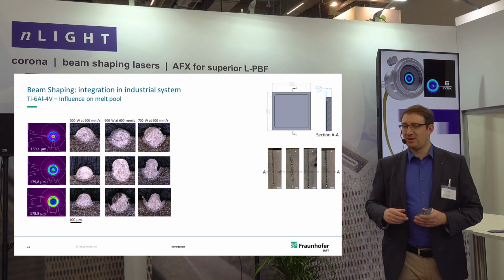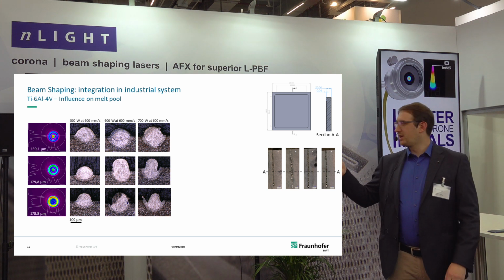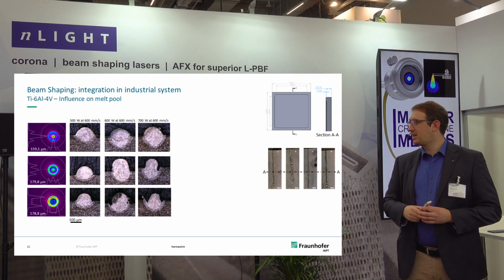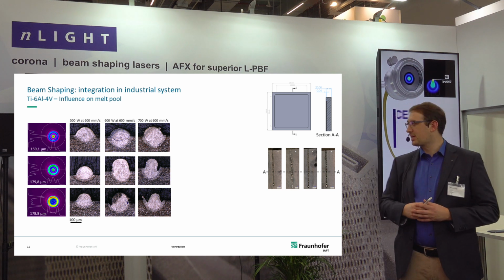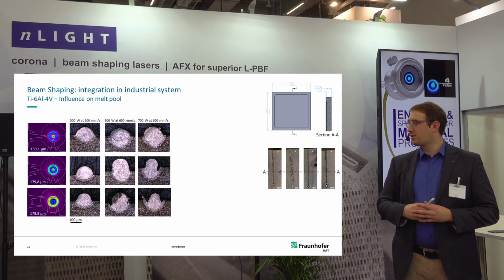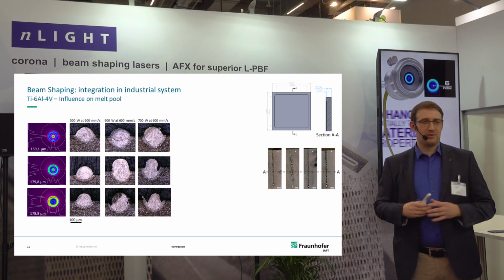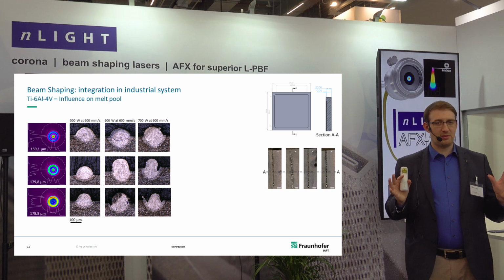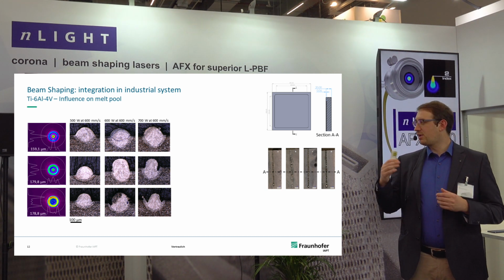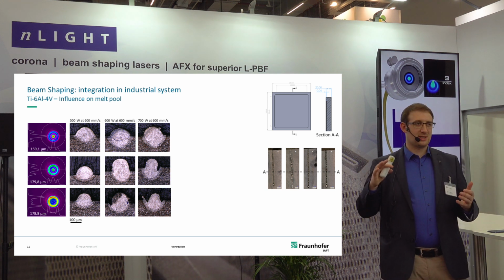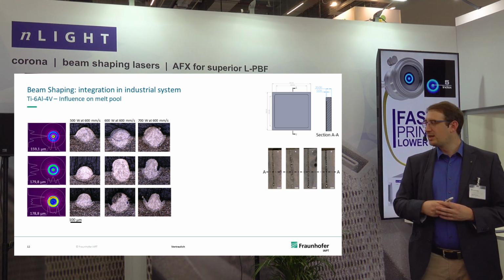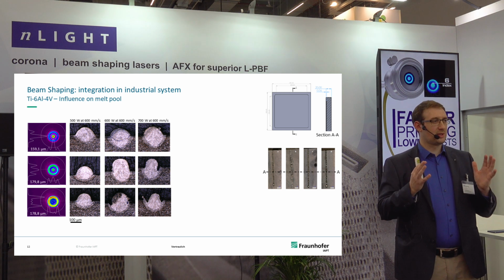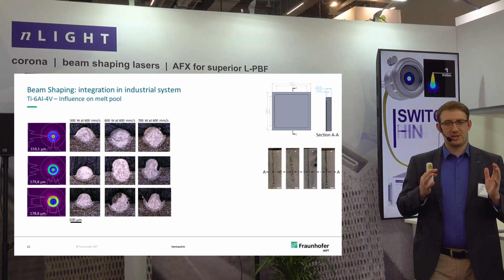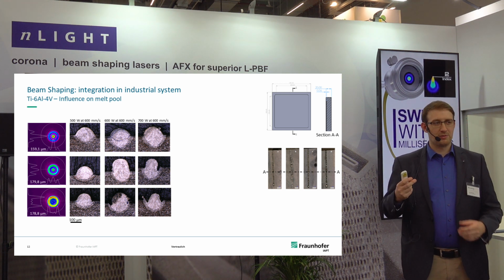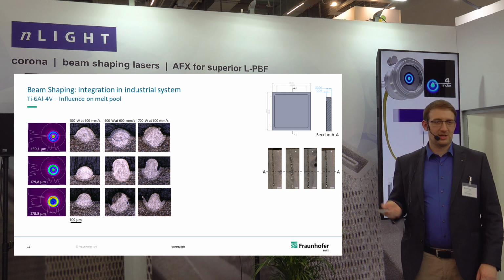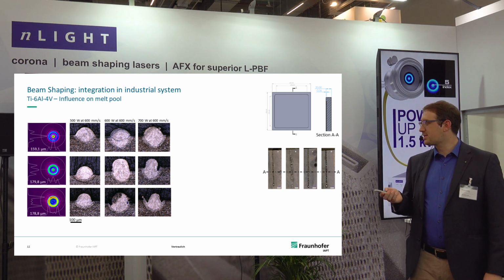And what you can see very interestingly, if we look at the 700 watt and 600 millimeters per second, is that for the top beam profile we have a very nice and very big weld track, while for the beam profiles in the middle and the bottom one, we have some protrusion. So this was quite interesting for us, that we have such a big influence between the different beam profiles.